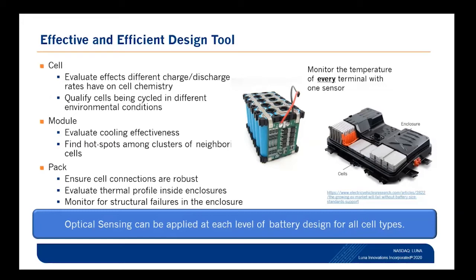Then once you take those cells and combine them into a module, you've got to look at different things like cooling effectiveness. Are you going to be able to draw the heat out of the center cells so that they don't cause a problem or enter into a thermal runaway condition? So that's finding hot spots among the neighboring cells. And monitoring it, so if a cell does start to go bad, say there was a manufacturing defect at some point that causes one to be weaker than another, the ability to monitor every single cell in the module is going to let you identify that much earlier.